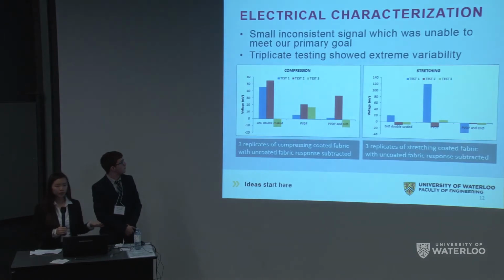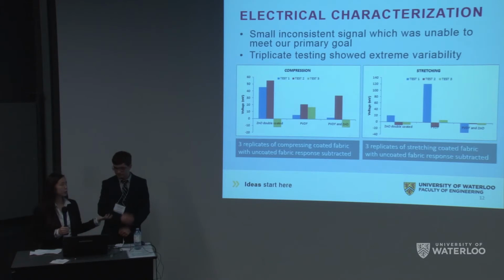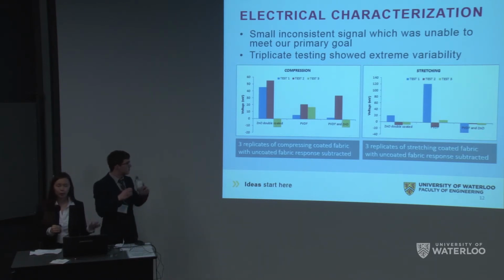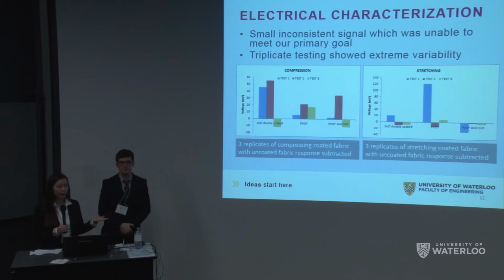So we performed electrical characterization with a multimeter, and we got these graphs. So you can see that the voltage we got was really weak, and furthermore, the results are very unreliable, and they were really hard to reproduce because we did this multiple times, and it was not consistent at all. So at the time, we predicted this was because of our poor coating, and we tried to improve our coating by submerging it multiple times, using different concentrations of nanowires, trying different ways of heating it to dry it.